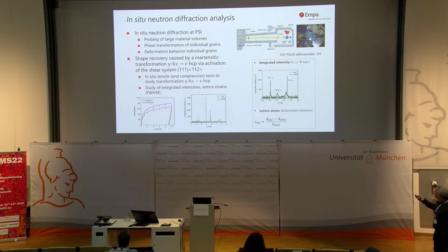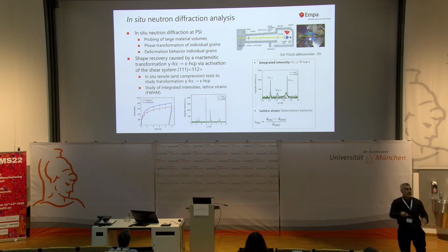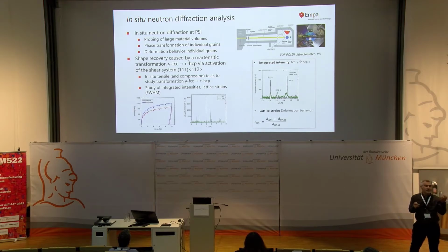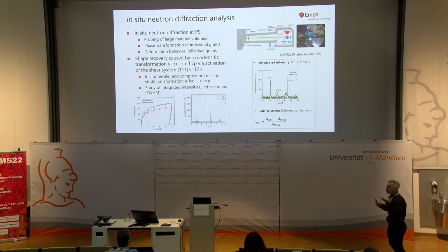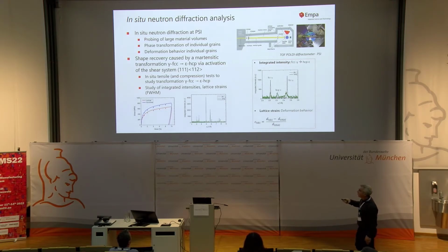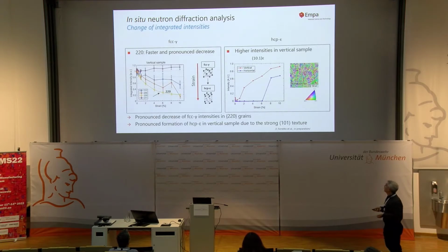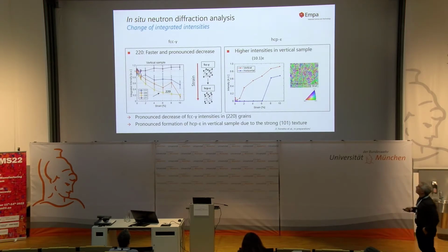So this is a diffraction pattern that we could get there. So we have very large gamma peaks. The epsilon is fairly small, already indicating that the amounts are not so high, and they are also fairly small in their geometries. So we did tensile tests, we interrupted those, did these measurements in situ, and then we started evaluating the data.